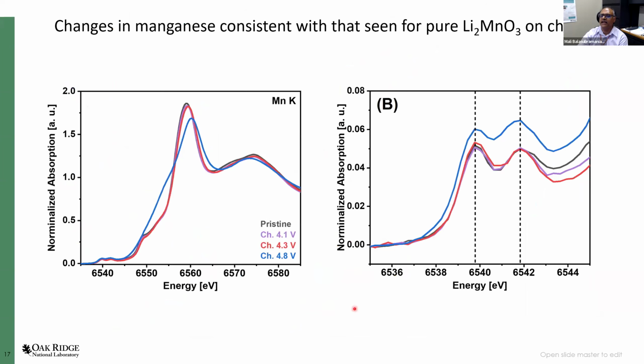So while that is true, we have also looked at the manganese, and the manganese spectra are just consistent with what we see for pure Li2MnO3, and we believe that there is no change in oxidation state, or actually in this case even the coordination structure of manganese. This behavior of pure Li2MnO3 is not seen in most other lithium-rich materials which are based on manganese and nickel. And this tells us that one of the failure mechanisms might be because of the way the material partitions, and the Li2MnO3 that is formed, unfortunately, is behaving like pure Li2MnO3, which we have shown in prior work, loses oxygen instead of creating any other oxygen activity which will be cyclable.